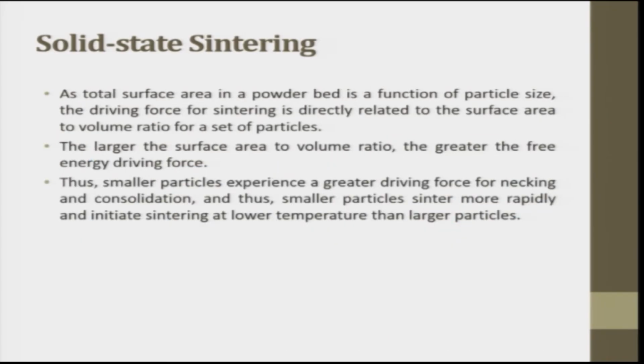As total surface area in a powder bed is a function of particle size, the driving force for sintering is directly related to the surface area to volume ratio. This is nothing but S by V. Okay. The total surface energy is related to S by V ratio of the particles. So, particle size and the volume of the particle, aspect ratio plays a role. The larger the surface area to volume ratio, the greater the free energy driving force. So, if the particle size is smaller and smaller, nanoparticles, the volume will be very small, surface area is very high. So, you will have a greater energy drive to push the particle.